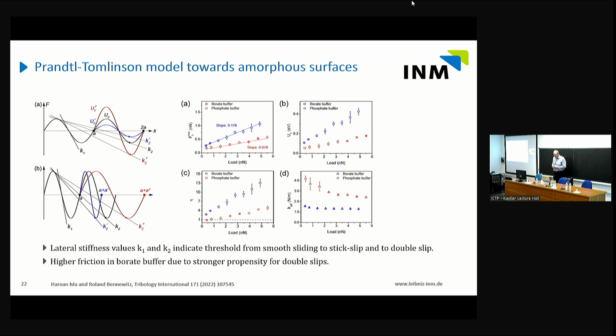And then he calculated essentially the lateral stiffness values K1 and K2, which indicate on the one hand the transition from smooth sliding to instabilities to stick slip, and K2 would be the value for the stiffness when you move from single slip to a double slip, when you just skip one minimum and just jump to the next but one, which Rob has shown actually is very important to quantify friction. And then he has simply analyzed the data we have, which is taken on the amorphous surface, and he has calculated all these little slopes, and he has calculated the slip heights, the maximum forces for slip, and done all the distributions.